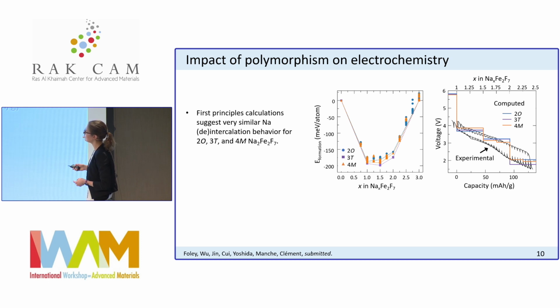So we get these convex hulls that Christine talked about in her talk. And what this type of data can give you is a way to calculate the theoretical voltage curve for these materials. So we wanted to compare these voltage curves that we were obtaining for these 3 polymorphs, and we're comparing this to the experimental data in black here. You'll notice that we have some big steps in the theoretical curves, and this is because we're not really computing every single composition in this compositional space, and we're not really accounting for temperature effects.